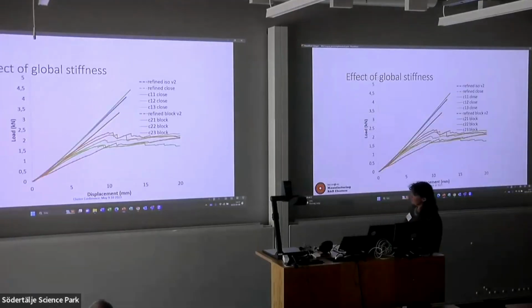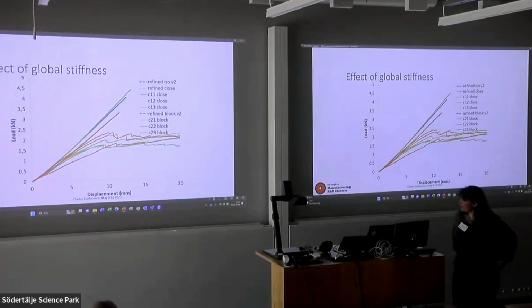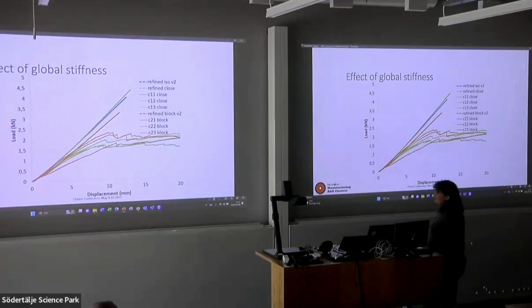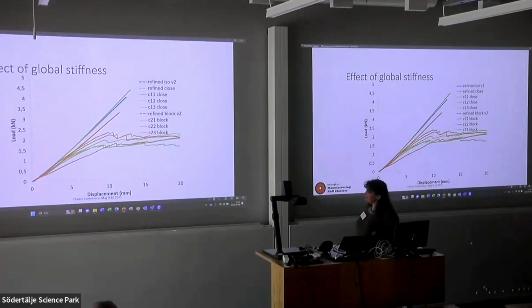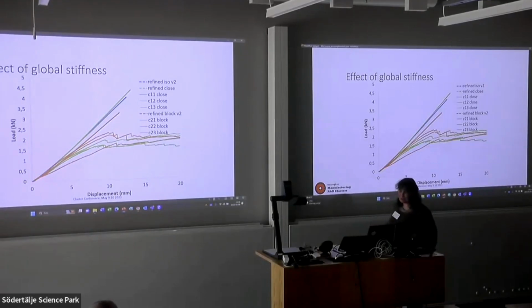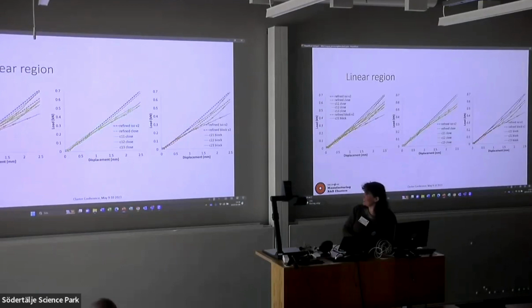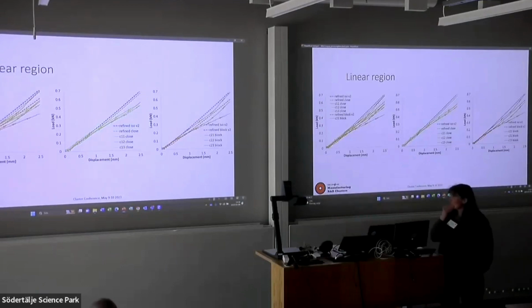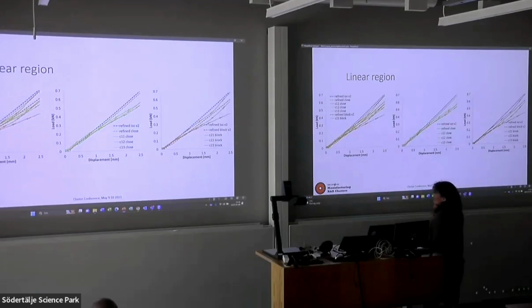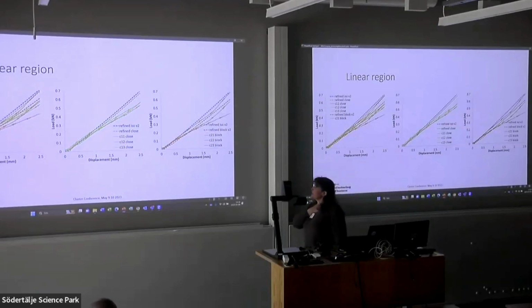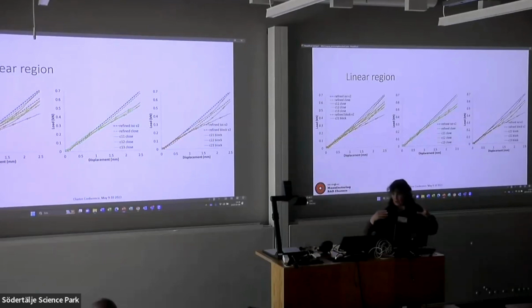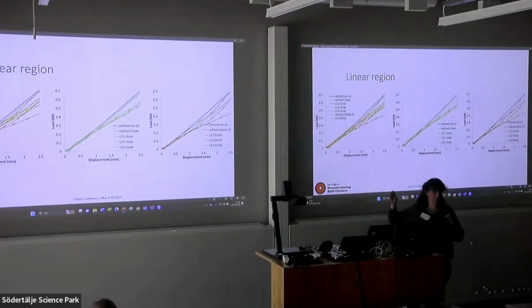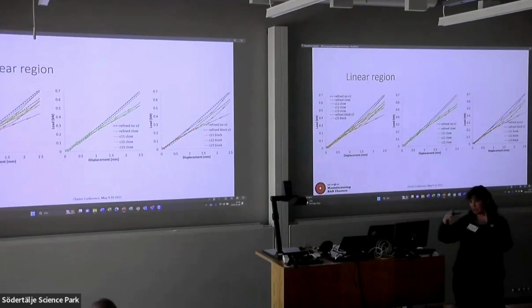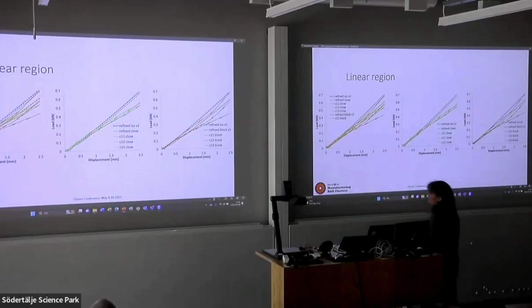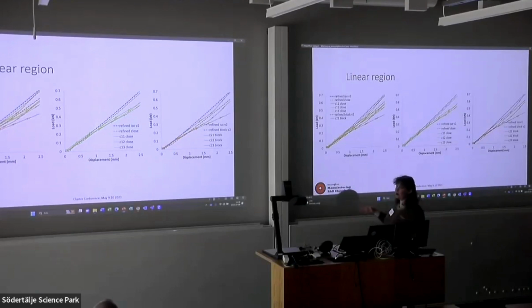So we looked at the prediction of the global stiffness. The blue line there is using the isotropic properties. We see, okay, it didn't make much difference. They all look pretty much the same. But if we look a little bit closer and take the linear part, then we can start trying to decipher a little bit more of what's going on there. For the net shape, there's much less variation, which is what you would expect because you've already draped it, so there's much less chance that it can vary. And it's also much closer to the isotropic values. Whereas if you're using a block, yes, you will fill the whole thing, but there can be a lot of variation in the experimental results.